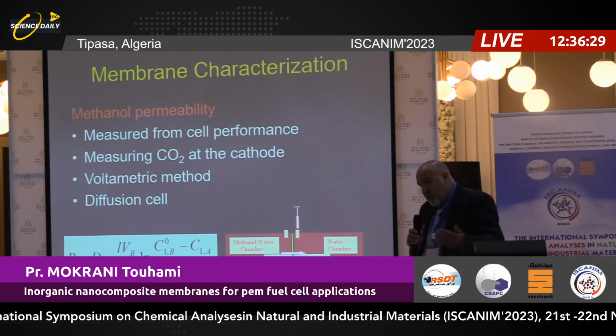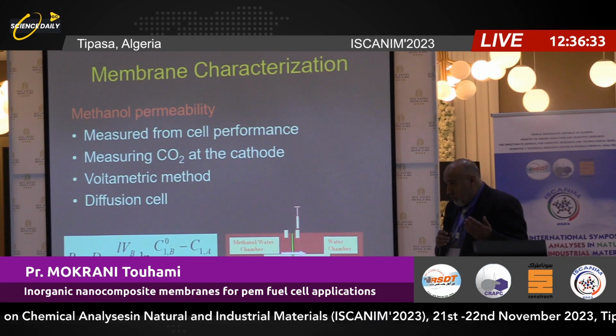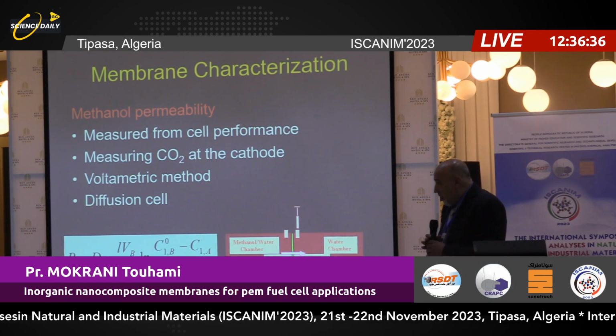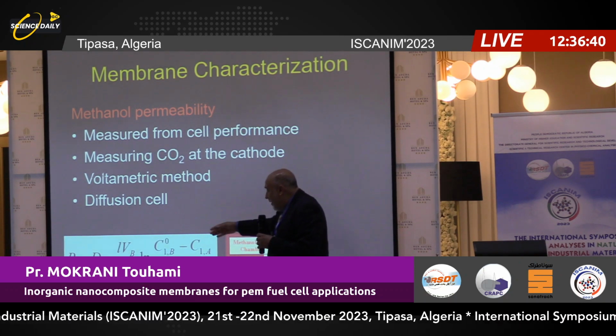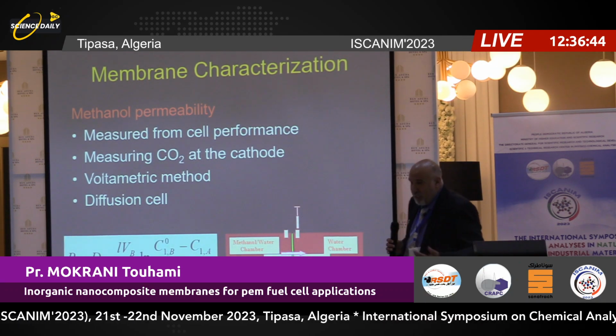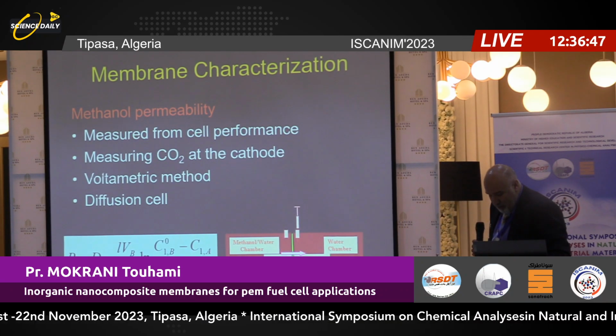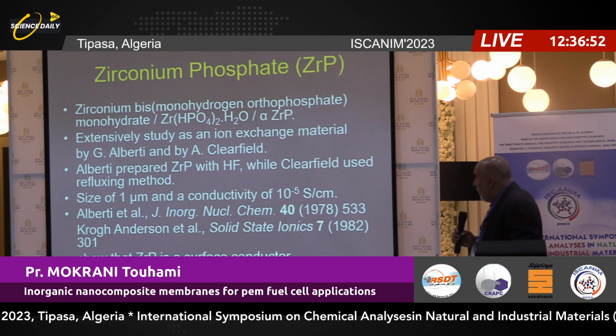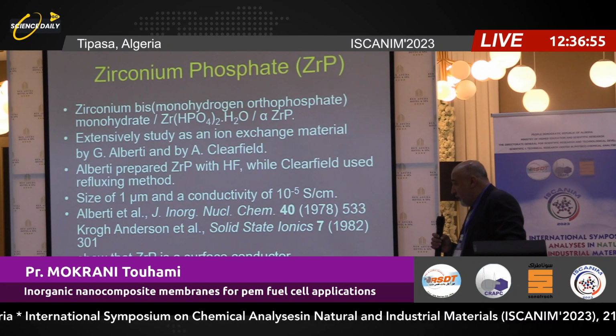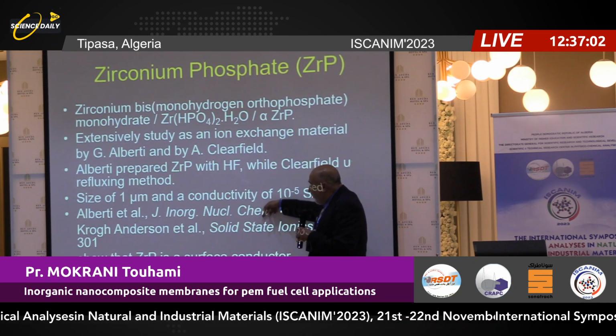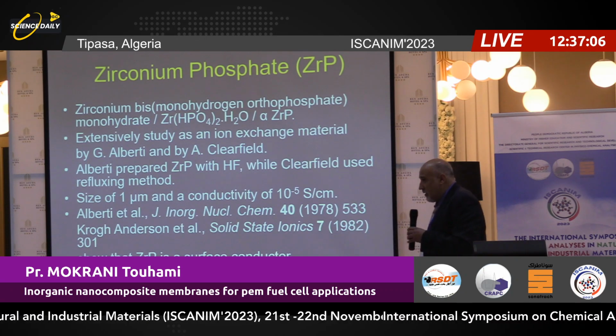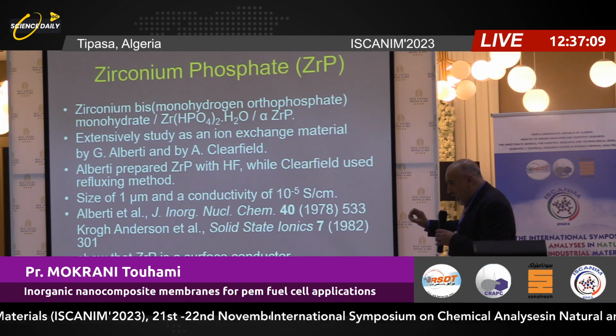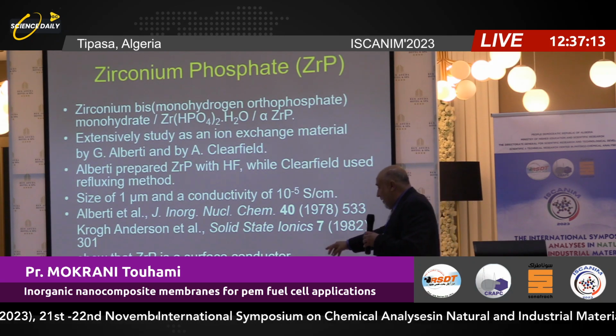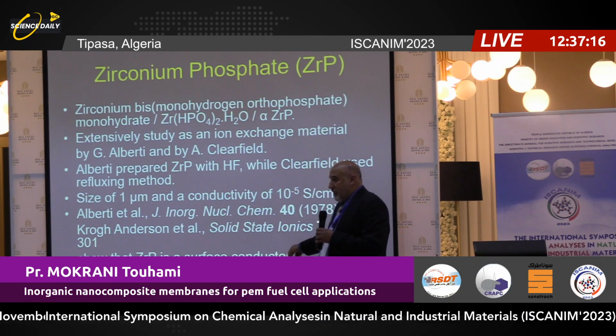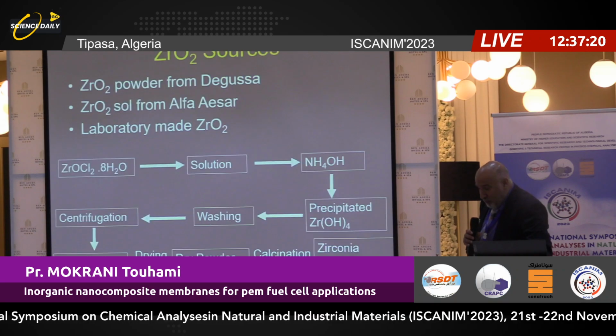This one is very important. As I said, we want to reduce the methanol, or we need to know how much methanol is going through the membrane. There are different methods to measure methanol permeability. We are using the last one, the diffusion cell. Because I am from the Department of Chemical Engineering, we know this method much better than the others. So we use zirconium phosphate, as I said, it's the best. The reason zirconium phosphate is the best is that it is a surface conductor. Previously these people used zirconium phosphate, or synthesized zirconium phosphate, but at a micro scale. If you have zirconium phosphate at a nano scale, it is a surface conductor, so itself is a proton conductor. And that's what we use.